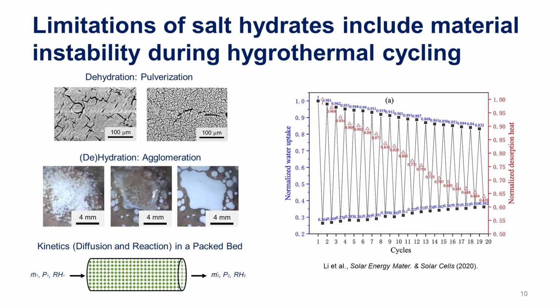For example, when we dehydrate our salt, so here's one of our salts, magnesium sulfate. As we dehydrate it, you notice that the salt pulverizes. So it breaks down into these much smaller structures. Or when we try to hydrate it, so here's the salt, and if you overhydrate it, you end up actually forming a salt solution. So now that's undesirable because we want the reaction to always be solid and gas. So we can either form a salt solution, or if you heat it at too high of a temperature, your salt can melt. And then you end up just forming this agglomerated block, and you lose the nice microstructure of the salt itself.